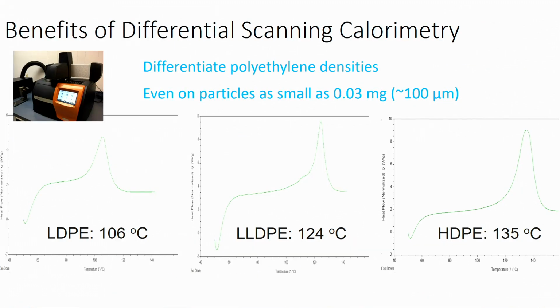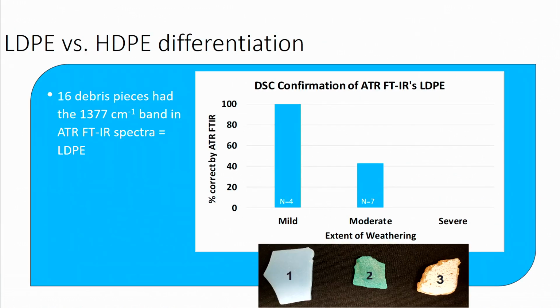And the reason is, if you start using a different method, differential scanning calorimetry, which is really good at differentiating low-density polyethylene from high-density polyethylene, shown here, see their melting temperature is quite different from 106 up to 135, so you can differentiate them very well. Once we started doing this, we started recognizing that we were a wee bit wrong. So this is our data to show that we were a wee bit wrong.